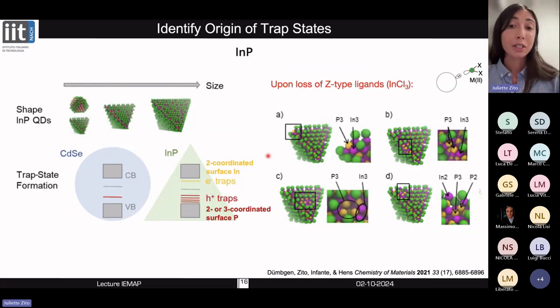And more recently, we did the same type of investigation also on indium phosphide quantum dots, and we again systematically modeled the loss of Z-type ligands from the surface. So in our models, these ligands were indium chloride 3 units, either from the corner, the edges, or the center of the facets. And here again, we found out that a reduced coordination of, for example, the surface phosphorus always gave rise to the formation of these deep hole trap states, while a reduced coordination of the indium atoms at the surface gave rise to electron traps.